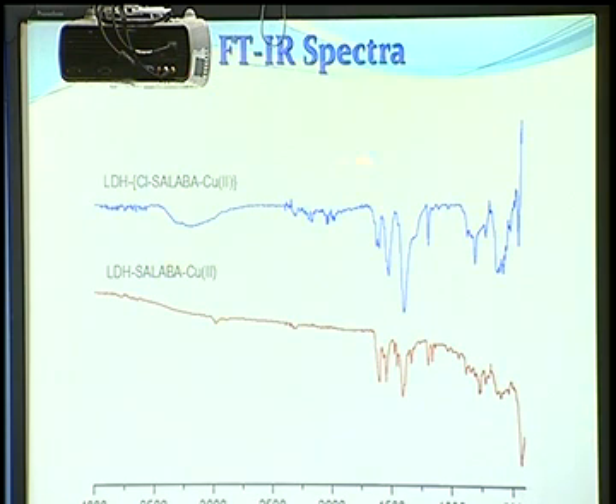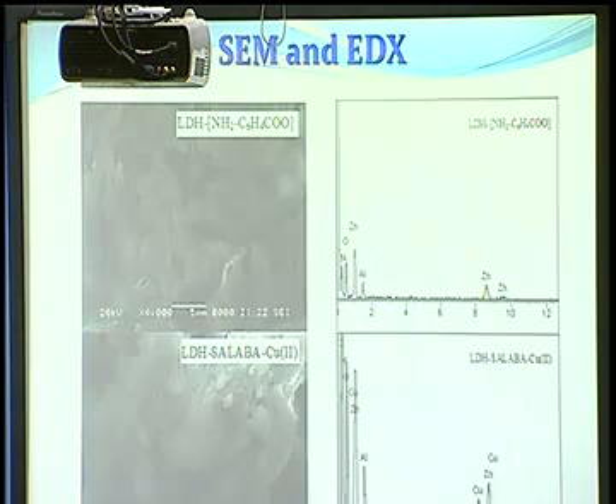This is the FTIR spectra, which shows some peaks. The peaks between 3100 to 3600 are due to OH stretching, and one more important peak at 1615 is due to the imine peak, C=N, which occurs in our ligand, and the peaks between 750 and 650 are due to metal-oxygen and metal-nitrogen stretching.